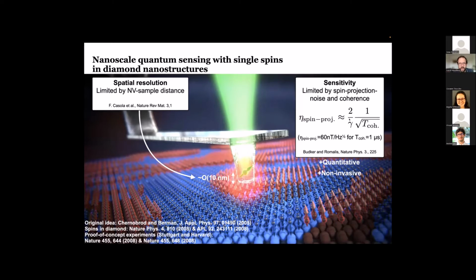And the point I want to make is that what is nice about using a quantum spin for magnetometry is that ultimately its sensitivity is really only limited by the laws of quantum mechanics. If you look into this process of measuring magnetic fields using spins, you will find that it is limited by quantum projection noise, where the readout of this spin is limited by the quantum postulates of measurement. It's given by this formula here, which essentially contains the gyromagnetic ratio of the spin you use for magnetometry, and the square root of the quantum coherence time of that spin. For most practical purposes, this is on the order of 1 microsecond.